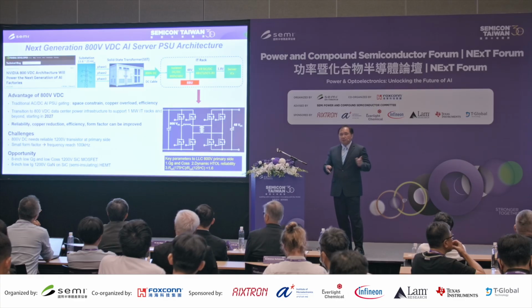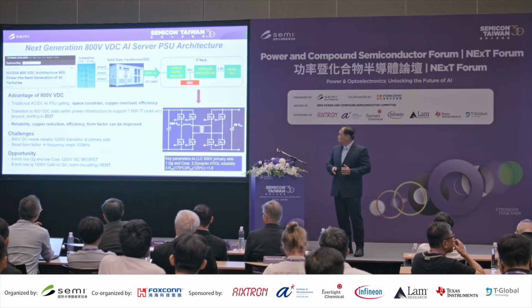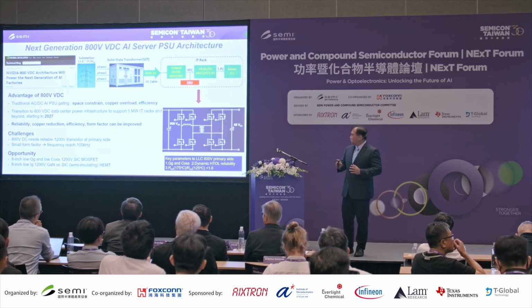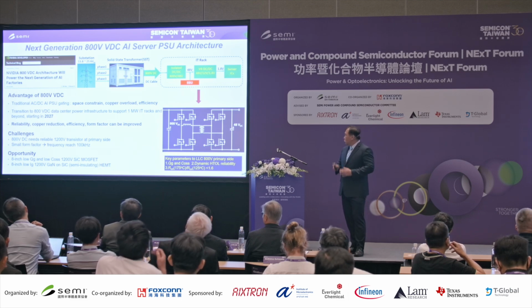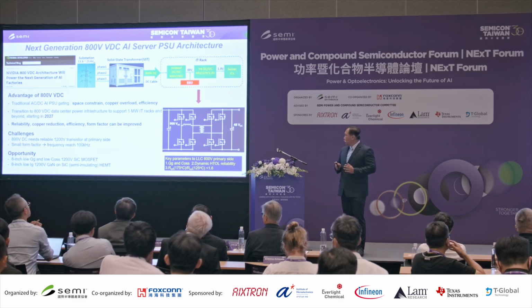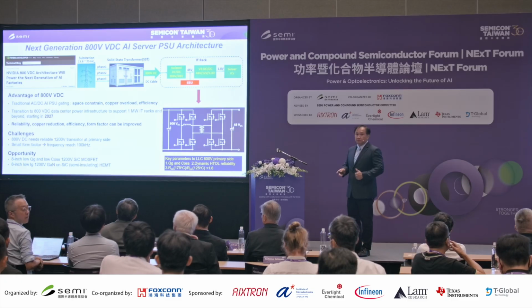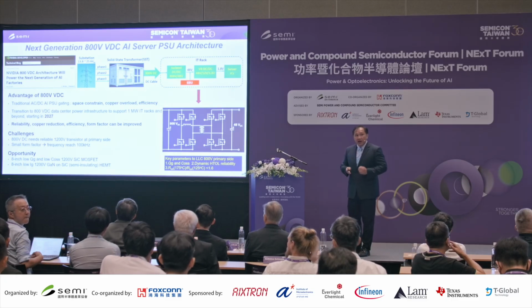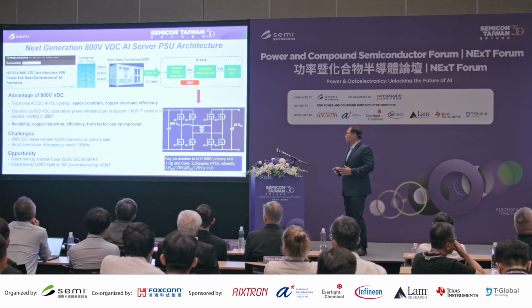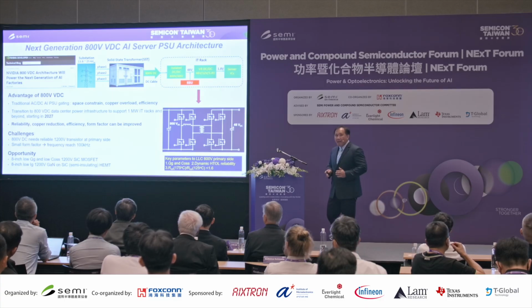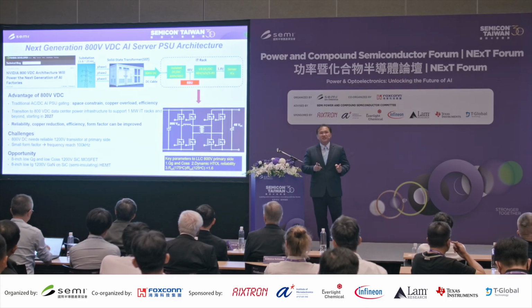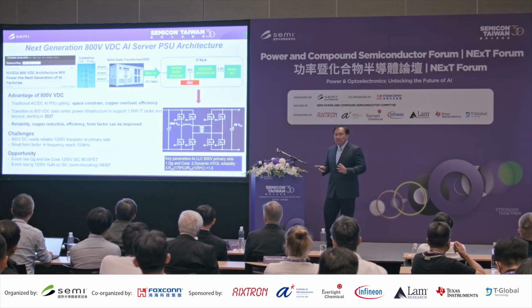And the opportunity maybe to point out, the first level, you can use the 8-inch low QG because the frequency needs to go to 100 kHz. So low QG and low COSS 1200 volt silicon carbide MOSFET would be the best choice now. But how about the 8-inch low leakage current 1200 volt GaN on silicon? Is it a semi-insulating substrate, not the N-type substrate?